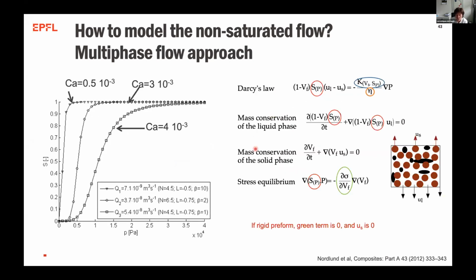The other approach, which is one that we have followed in the past and are still following, is to use a fully unsaturated multi-phase flow approach. So where you look at fluid flow, not only you don't assume that everything is fully filled, but you have porosity here. So you have a volume fraction of pores that is also present. So the volume fraction of liquid is also something that you need to know. And you also have possibly, in that case, velocity of the solid, we can say it's 0. But we need to know the saturation, so the ratio between the liquid and the solid phase.